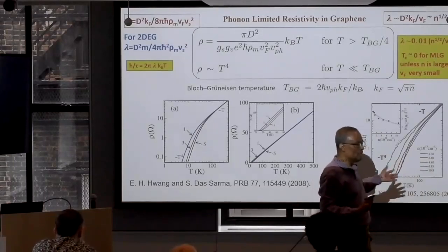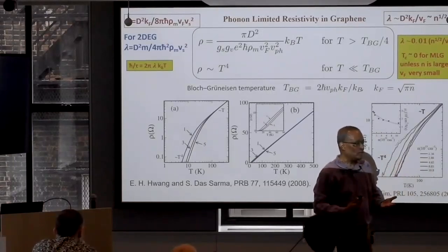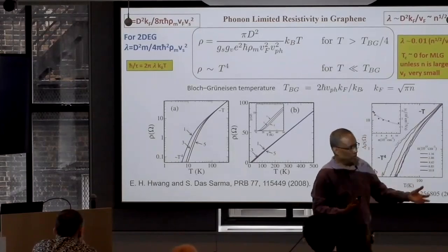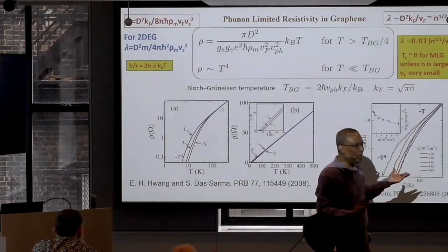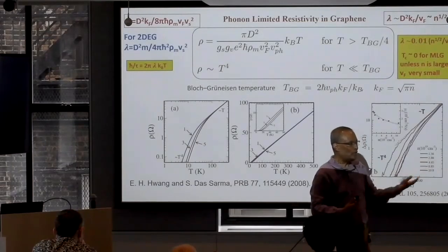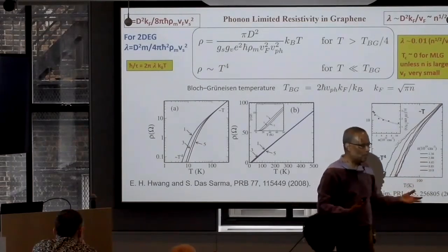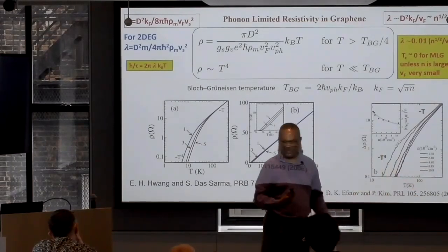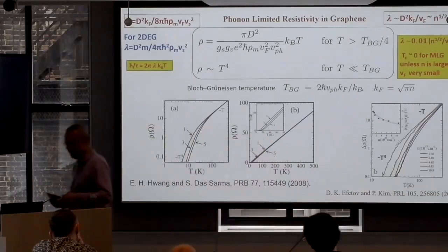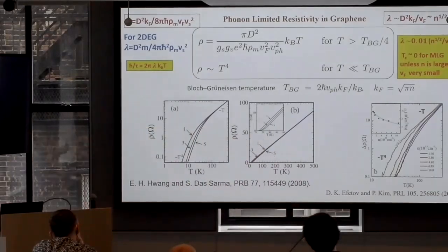In graphene, disorder-induced temperature dependence is not there because it doesn't have the Fermi surface anomaly, since it's Dirac. So 2kF disorder scattering doesn't have strong temperature dependence. It's not important. I don't remember the residual resistivity, but it was not an issue. But it's a good question. In some other materials, it could matter.